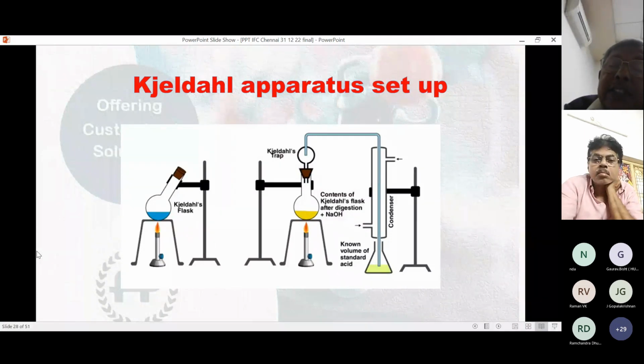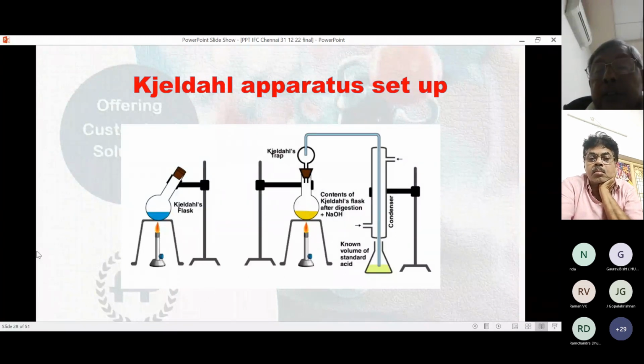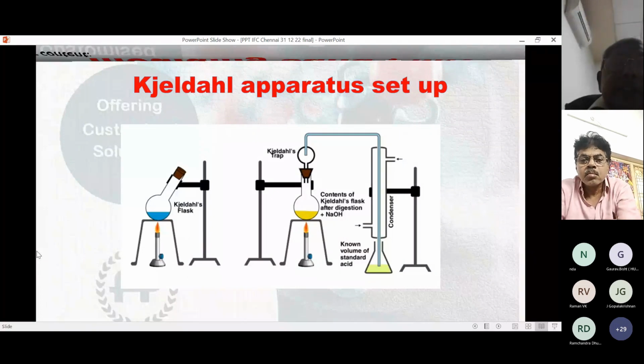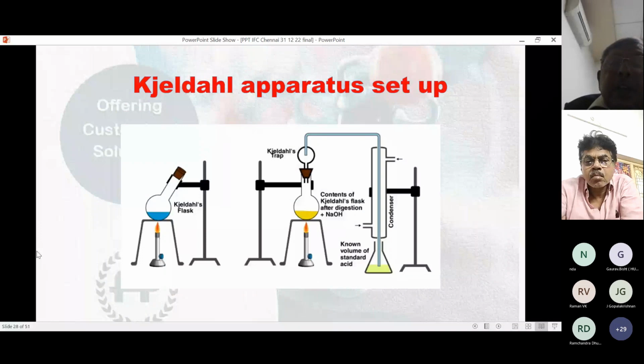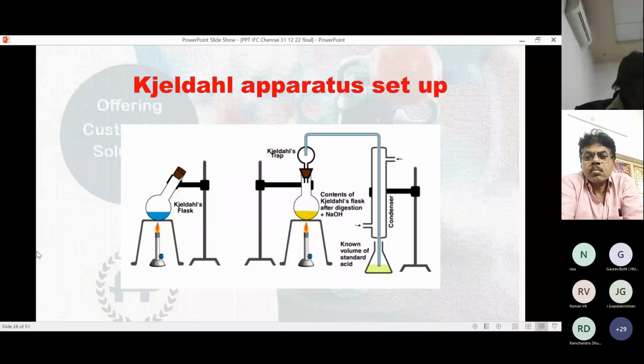And when you are using a small quantity of standard acid, the ammonia liberated will consume acid to some extent, and the excess acid is titrated with standard alkali, or standard acid using methyl orange as indicator. So 17 grams of ammonia will form 14 grams of nitrogen. So based on your input weight, you can calculate it as a percentage.